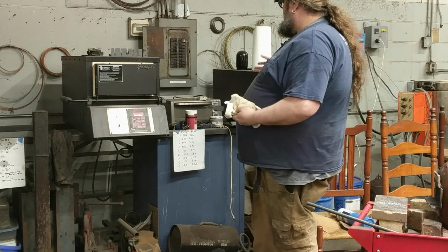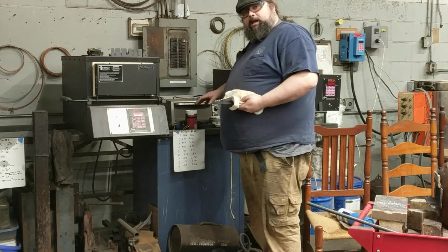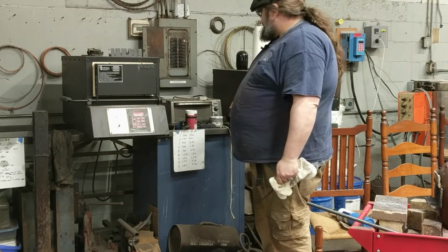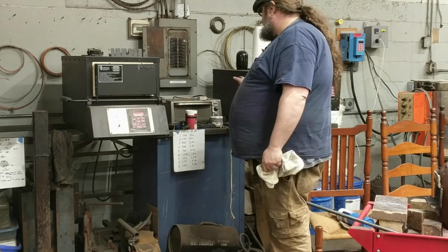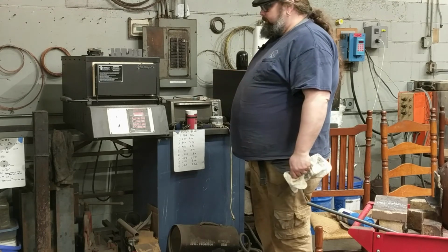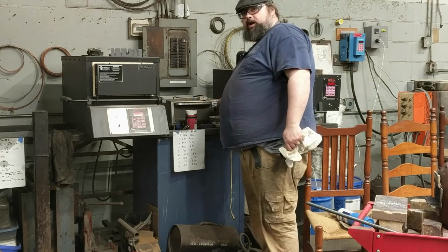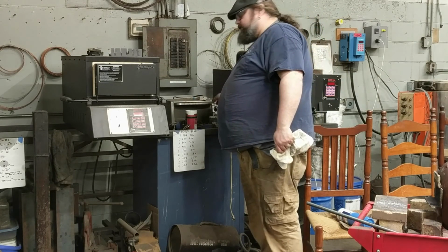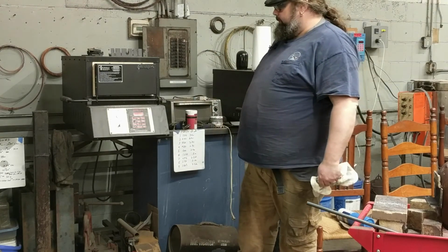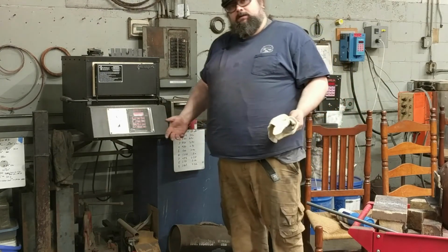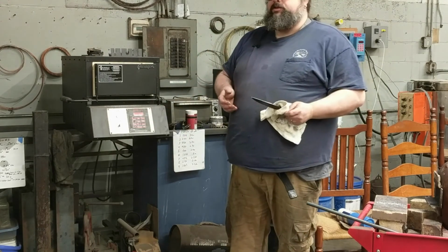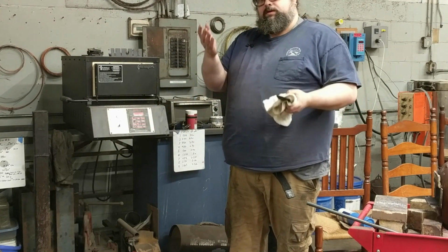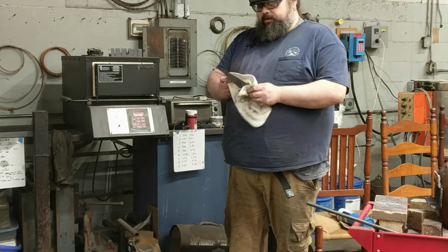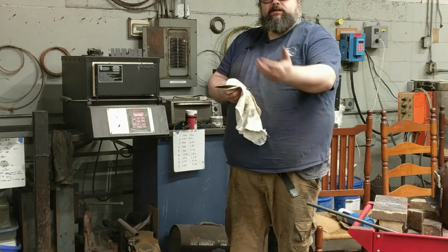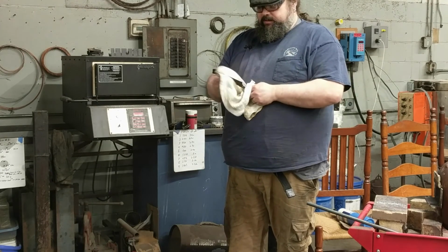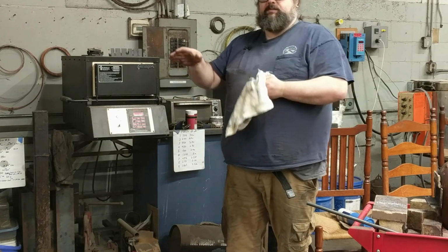And all we do is, we had a little oven thermometer we stick in there and a piece of hard fire brick and just let it run for a while at 350 degrees, 375, whatever it was. Let it equal out and then mark on the dial where each of the temperatures are. This one maxed out, if we did it at 400 degrees, it was 375, that was all it would ever do. You can also use a kitchen oven, same thing. They hold temperature fairly well, but they don't always give you the right temperature.